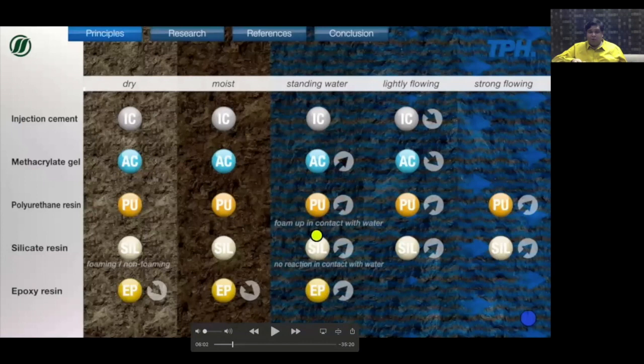Silicates are very, very apt to use in almost all these conditions, like standing water or lightly flowing or even heavy water flows. Epoxy systems you can use up to a point, but from this point on, they're not very effective. So when you have the problem of standing water, or slightly flowing or even heavily flowing water, I think the best systems you can use are PUs and silicates. And methacrylates can go up to, I would say, lightly flowing water.